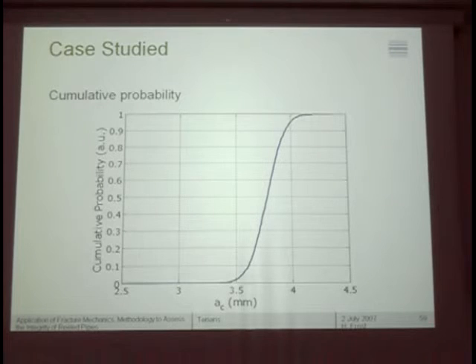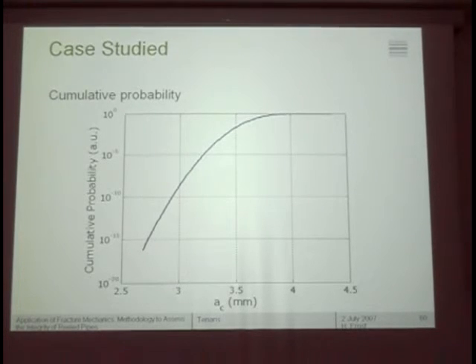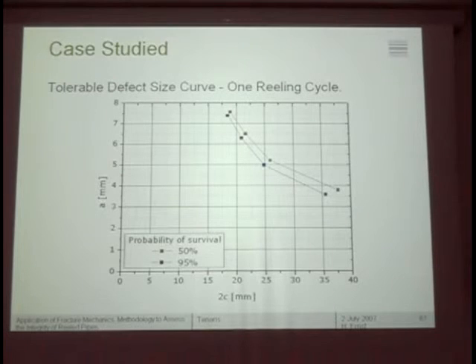This is the cumulative probability of that, and if you want to see that in a better scale, this is what it looks like. Just to make things a little more clear, and as I many times said, even if you didn't understand too much of what I said, it doesn't matter if you look carefully at the next 2 or 3 slides. If you have a defect depth A in the vertical axis and a defect length 2C in the horizontal axis, these lines will give you, in this case, the 50% probability of survival for this material and this history of deformation, and this other one 95%. Okay, this is the combination, millimeters versus millimeters, so no J, CTOD, Paris law, delta J, anything like that.